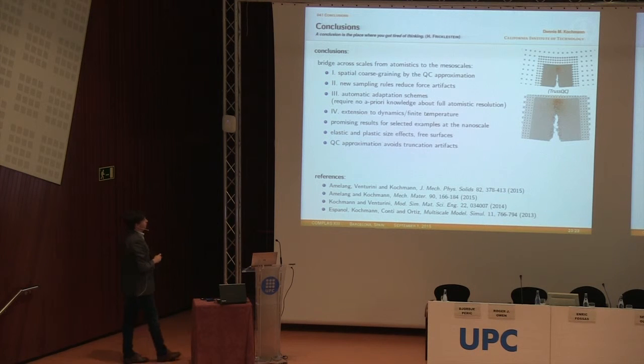That's a very nice way that we can do here because we don't have an interface between the two regions. The fourth, I briefly mentioned, was dynamics and temperature. We have seen some interesting results for selected examples. We see elastic plastic size effects. Free surfaces are accounted for. And as I mentioned, it avoids truncation effects of your unit cells. So you can easily do very big calculations without boundary effects.